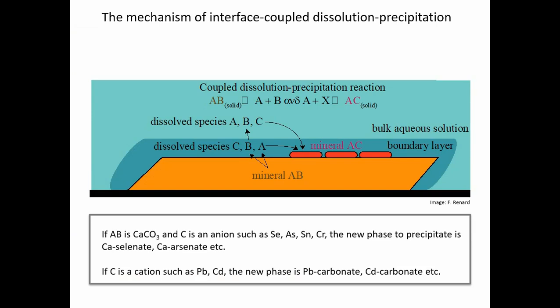Okay, so we can summarize that, and here I've drawn a little, it could be any crystal, any mineral, but it looks like calcite because it's rhombohedral. We have a solution containing element C, or ion C. The mineral, for example, calcite AB, is calcium carbonate. In that fine fluid layer at the interface, we're getting the release of calcium carbonate ions, and we're getting the formation. If we can supersaturate with respect to a new phase, it could be calcium and an anionic species, such as arsenic or selenium, or it could be, for example, cadmium carbonate if C is a